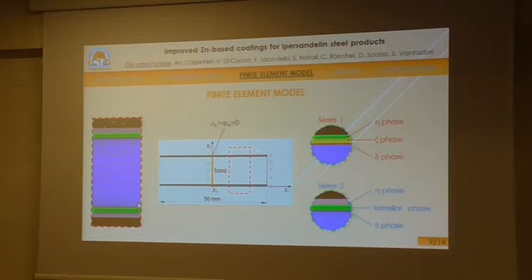For nodes along the x2 axis, displacements along the x1 axis and rotation around the x3 axis are taken equal to 0. And for nodes along the opposite extreme, rotation around the x3 axis is applied by increasing half bending angle from 0 to 35 degrees by considering a suitable interval angle. Here you can see a zoom of the coating for series 1 and series 2 specimens.